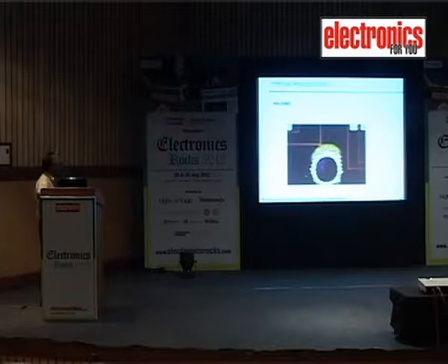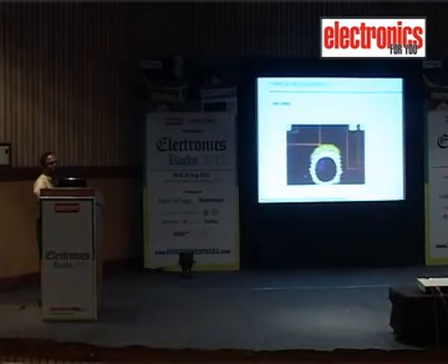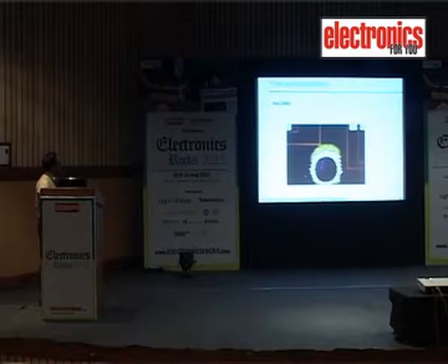What will happen is, if the entry sheet or the backup sheet during the manufacturing is not properly put, or if an old drill bit is used, generally what we do is we limit the number of hits to 300 hits only. If we exceed that number of hits, the drill bit gets worn out, and if you drill with a worn out drill bit, this is the rupture caused on the laminate. You can see the rupture extending up to the trace. So the whole zone becomes weak, and such PCBs are rejected mercilessly.